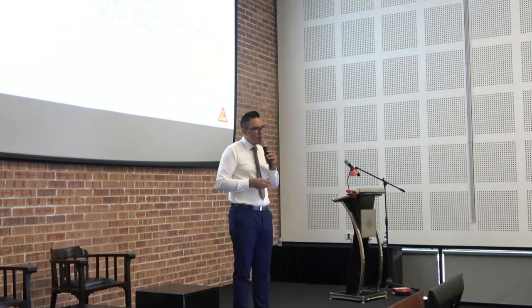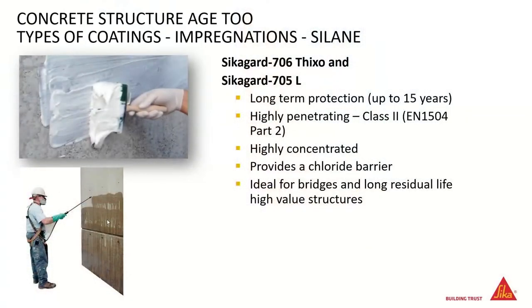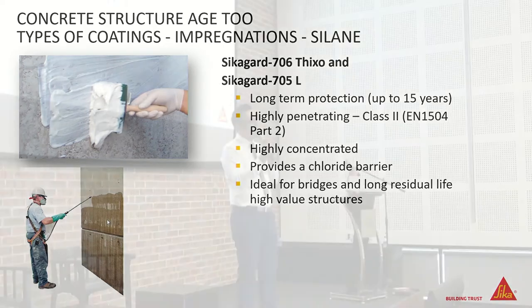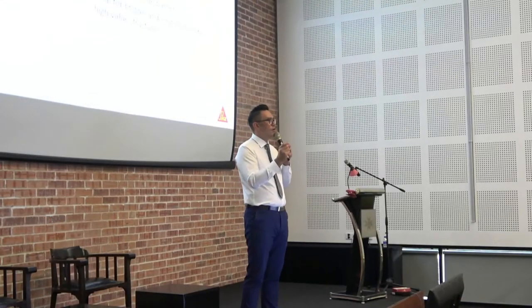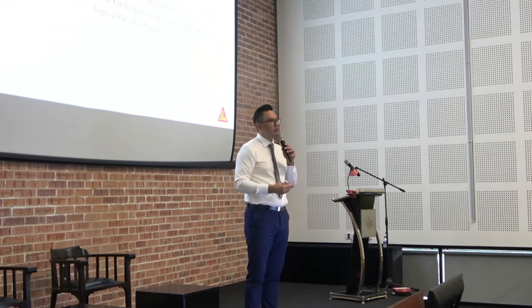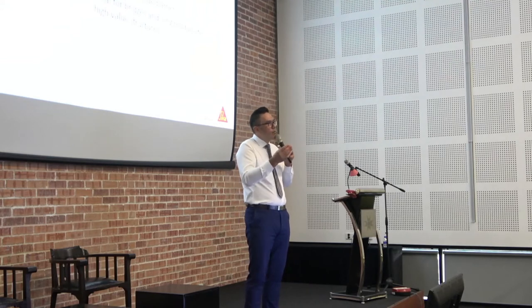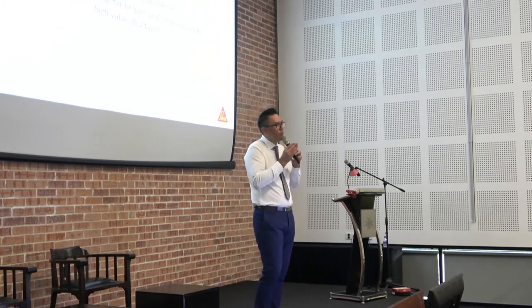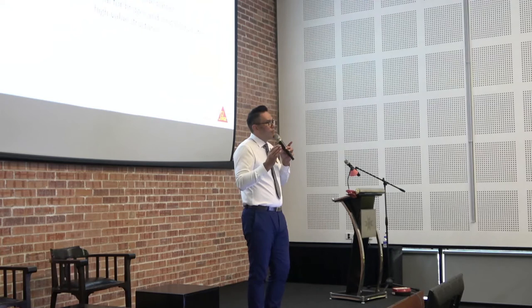And what it also means is that if there's some minor flaws in the construction, say the concrete beam looks like this, but the cage might have moved in placement and the 40 mm coating of concrete to give the life expectancy might have dropped down to 33. By applying something like this, we can increase the theoretical performance of the concrete again.